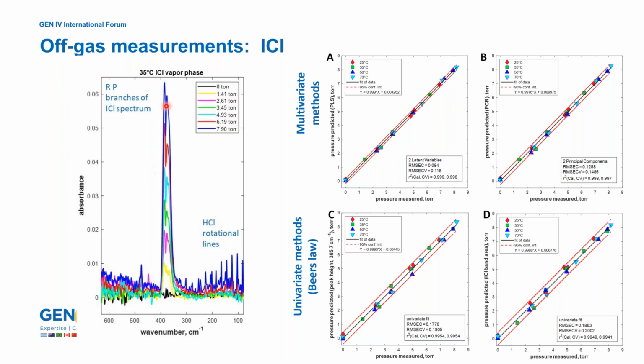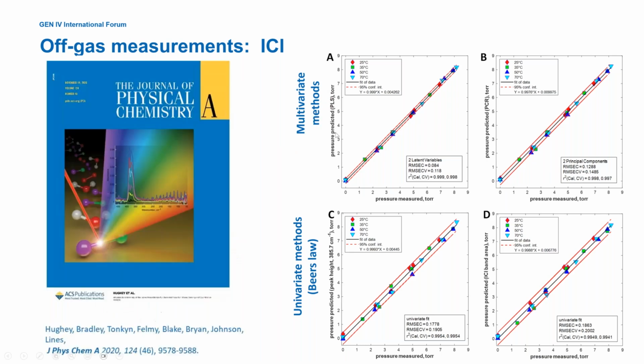Some of my colleagues say, this is such beautiful data. Why not just use a single variate analysis, just peak height, for example, or peak area under the curve? Well, we can do that, and they form really nice models. But in this case, the univariate methods, while they work very nicely, this is the peak height versus a concentration curve, and this uses the peak area for concentration. You can tell that the models are not quite as accurate, and they have a lot larger error bands than the multivariate method. So again, this shows that multivariate method works very nicely for this kind of data. And this work was summarized in the Journal of Physical Chemistry and published a couple of years ago.